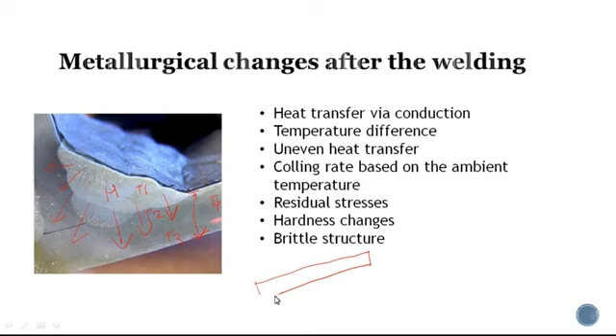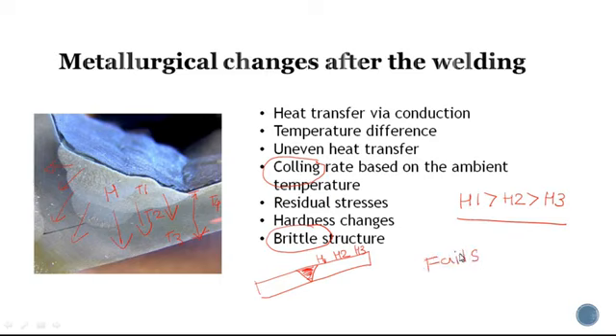To understand hardness, let's see an example of a weld cross-section area. As you can see here, there are hardness values H1, H2, and H3. These hardness values are at different locations from the weld metal, and because of the cooling, hardness changes. There is always a higher hardness near the weld area and lower hardness further from the weld area. Because of the different hardness, it makes a brittle structure, and a brittle structure fails whenever heavy loading is applied.